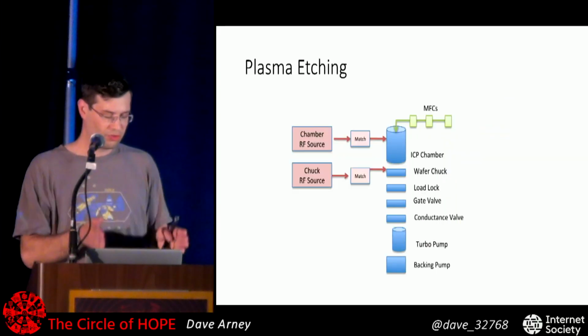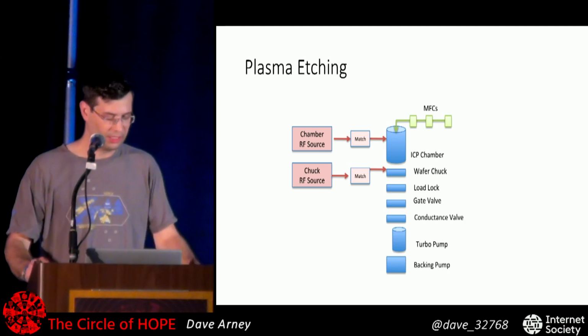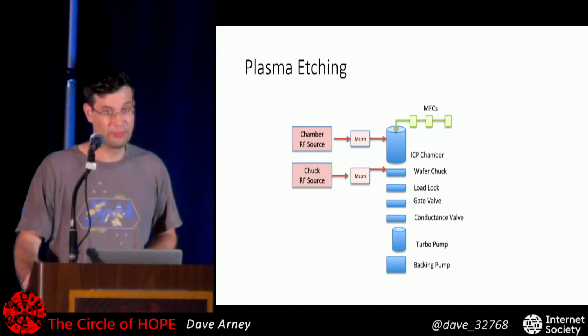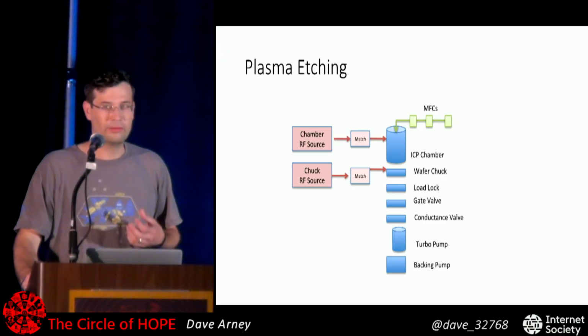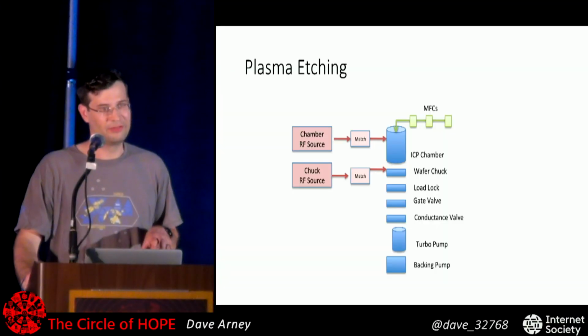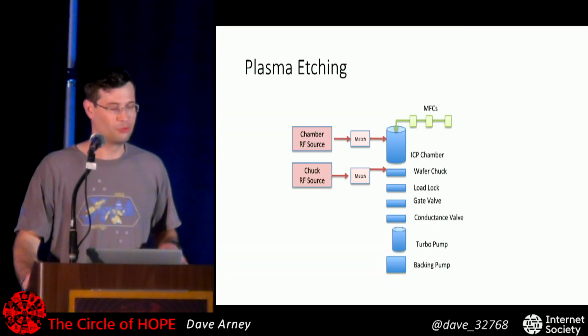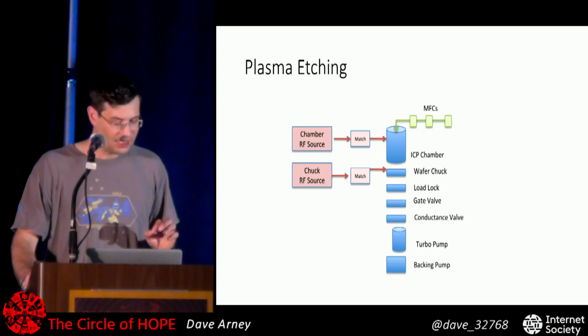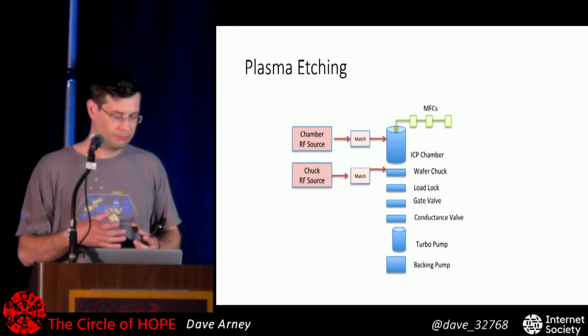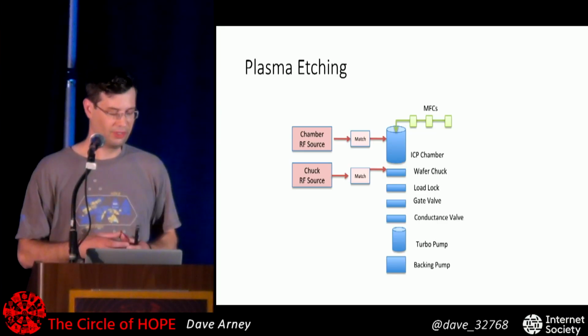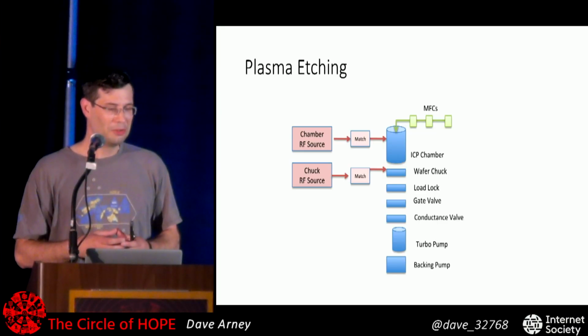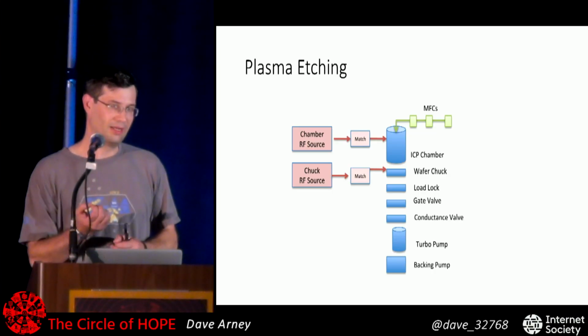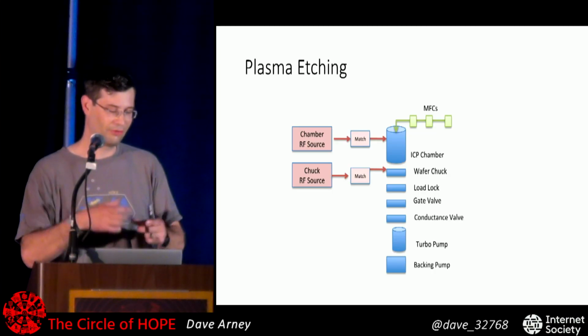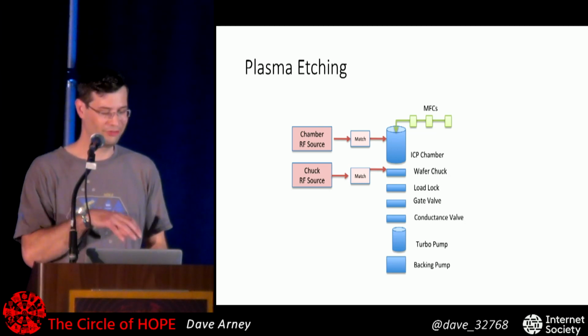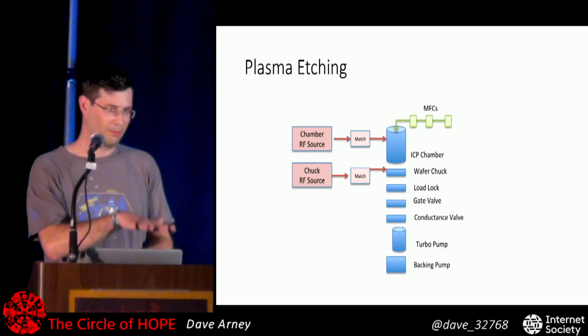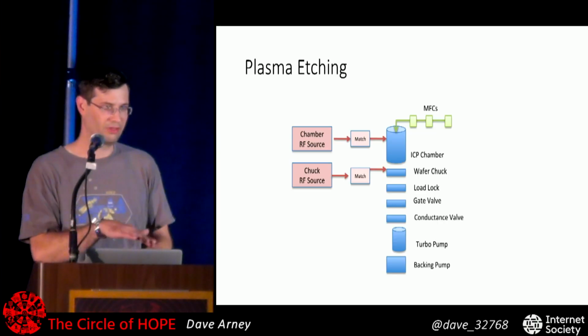To do anisotropic etching, to get straight edges on your parts, it gets more complicated. And the process that I've really dug into is plasma etching. One of the original versions of this is called deep reactive ion etching, which was patented by Bosch more than 21 years ago, and involves putting your wafer into a plasma chamber with the right composition of gases, so that you get ions that will attack the silicon, and accelerating those ions down toward your substrate, so that they hit both the masked and the unmasked parts, but selectively etch away the silicon that hasn't been masked.